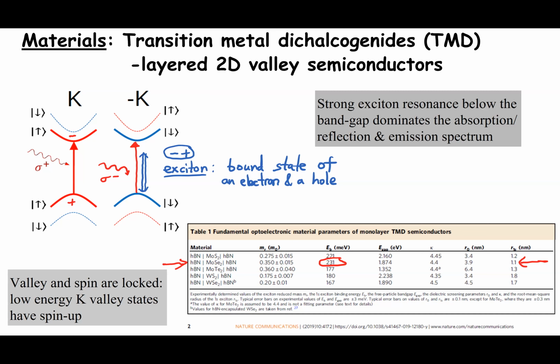That's the elements of spectroscopy. What is really nice is that we can resonantly generate excitons optically by photon absorption, but what we generate when we absorb a photon is not a massless particle, it's actually a polarization wave which has a finite mass. It consists of an electron-hole pair, so it's a polarizable object, so it interacts with each other as well as with the electrons or the holes that you have in this. That's what we're going to use in spectroscopy: by converting an exciton into a quantum of polarization wave, we can enhance the interaction between the optical excitation and the electrons.